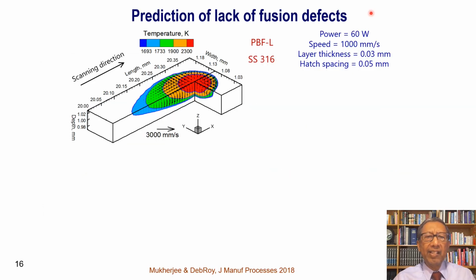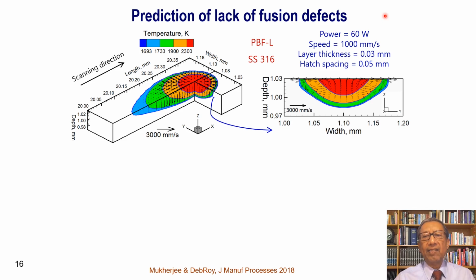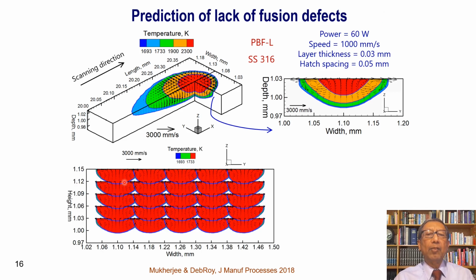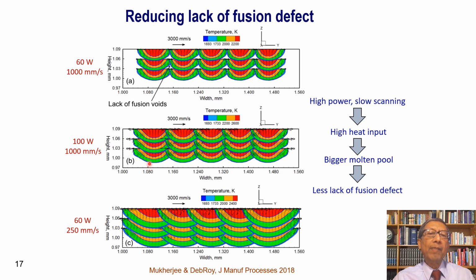A well-tested heat transfer and fluid flow model can calculate the fusion zone geometry in different hatches and different layers. And unmelted regions between the two consecutive tracks and layers indicate the lack of fusion defects. To make a fully dense part, there needs to be sufficient overlap among different adjacent hatches and layers. For a given alloy, higher power and slow scanning will result in larger fusion zones and less lack of fusion defects. And just the opposite will also happen.